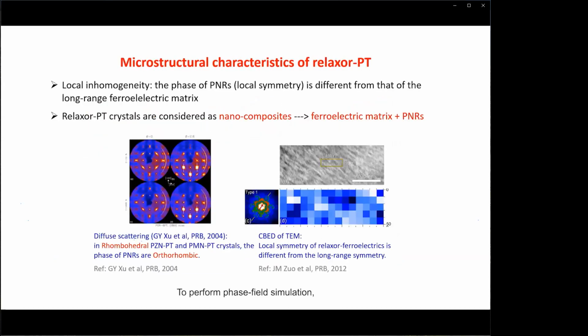To perform phase field simulation, we have to know the microstructure characteristics of Relaxor-PT crystals. The main characteristic is the local structure heterogeneity, as observed by diffuse scattering and TEM experiments. For example, diffuse scattering experiments showed that orthorhombic polar nanoregions are present in rhombohedral Relaxor-PT crystals. Thus, in our simulation, we consider the Relaxor-PT crystal as a nanocomposite.